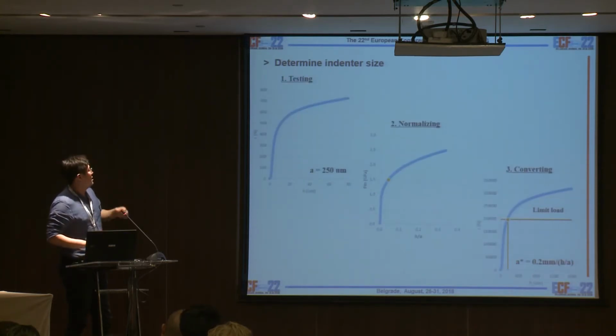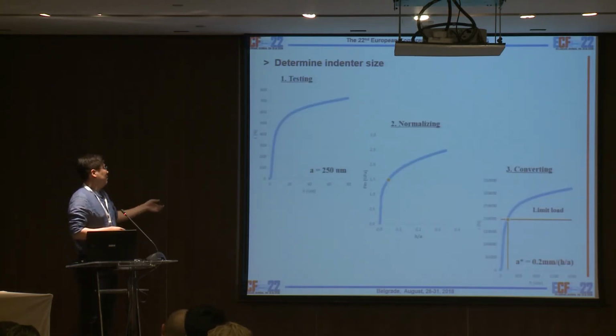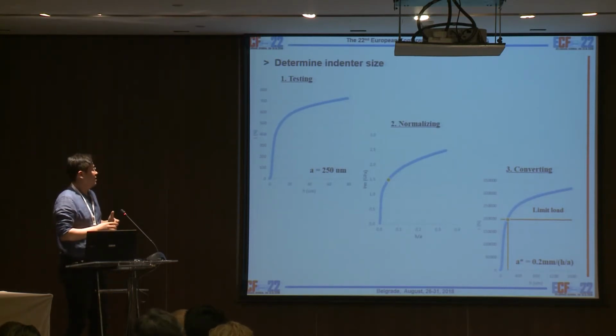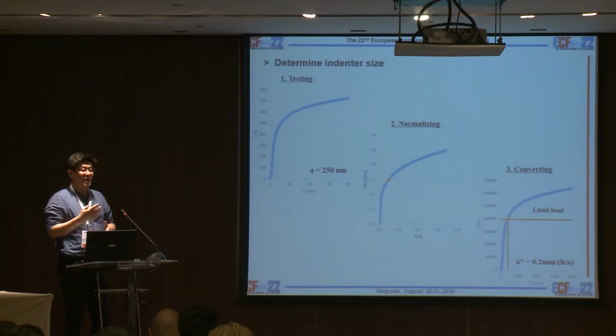Then we test with the 250 micrometer radius indenter and normalize it, and set the limit load as the correct initiation point. And after that, we know the H of A point and recalculate with a star 0.2 millimeter, and we can get an A star virtual indenter radius and indentation curve.